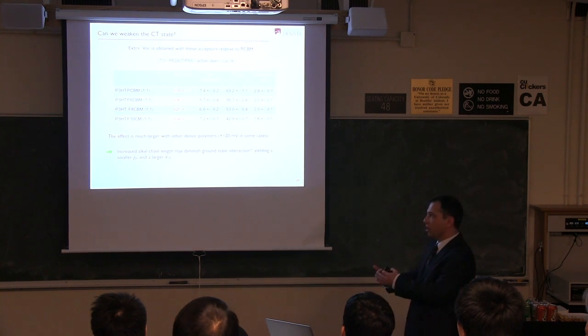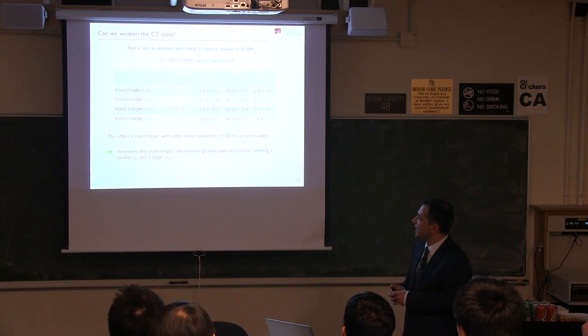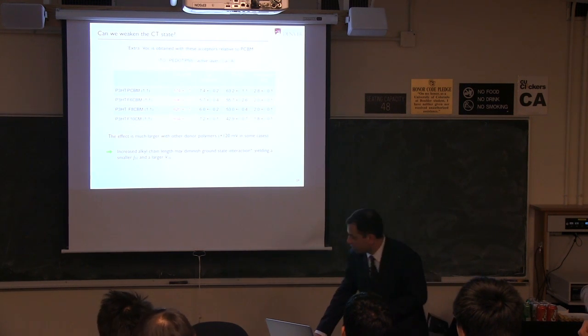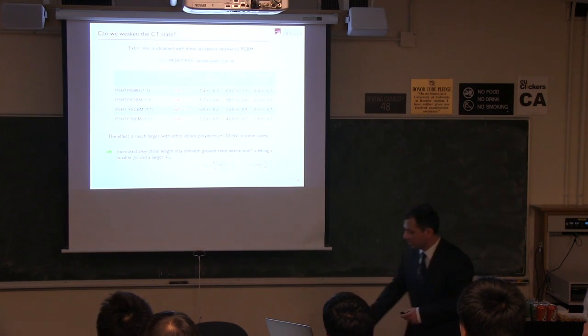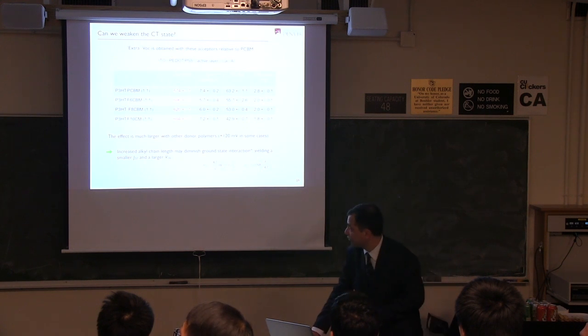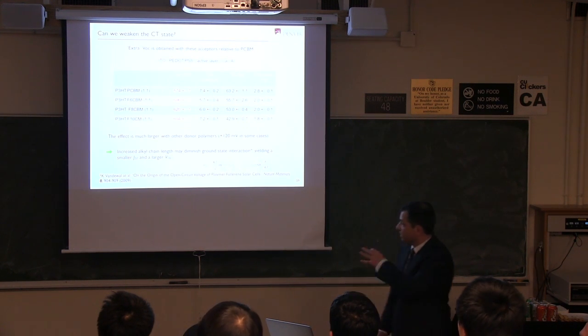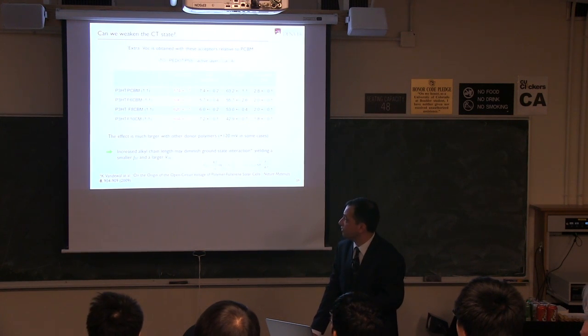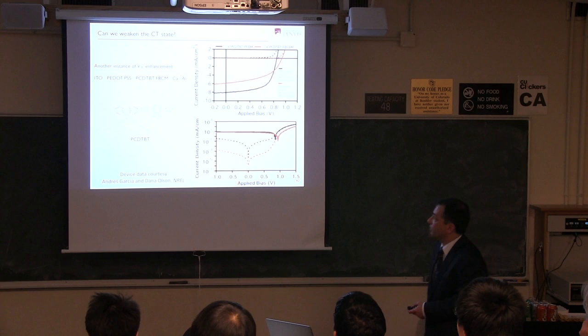In other systems, we can go much higher. I'll show you data in a second. We can push the voltage up by about 100 meV. So what do we think is happening? That longer alkyl chain is reducing the ground state interaction, the CT interaction. That makes a smaller reverse saturation current in the ideal diode equation, and that gives us a little higher voltage. So J_S shows up on the bottom here of the logarithm of the voltage. That was work where the theory was worked out by a person who's now at Stanford, Koen van der Wal. Like I said, we've done that with other materials.